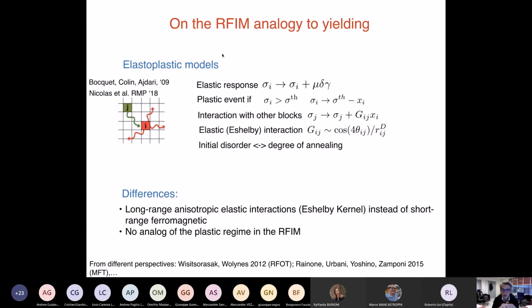And then, what we want to study is different amorphous materials. What changes between different amorphous materials is the degree of annealing. This is our idea. The different behavior between foams, colloids, and metallic glasses is actually due to the fact that metallic glasses have a very small amount of disorder, are much more annealed, and foams, for example, are much less annealed.